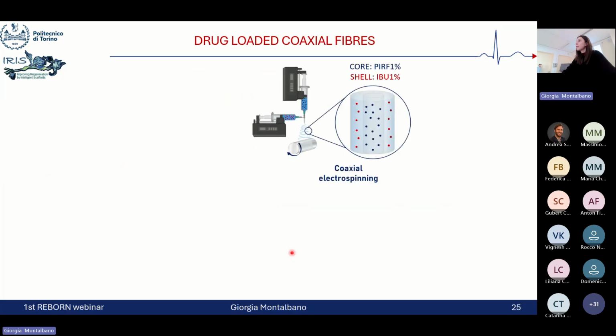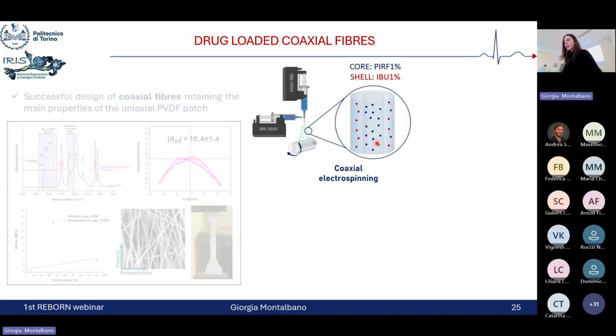But then we wanted to explore if we could better modulate the release of the drug. And so, in order to obtain a faster release of the drug incorporated in the outer part of the fiber and a more prolonged release of the drug incorporated in the core, we exploited the coaxial electrospinning setup. So here the first assessment was performed introducing pirfenidone in the core and ibuprofen in the outer part of the fiber, using the same concentration in order to better understand the influence of the distribution of the drug in the fibers on the release of both drugs.